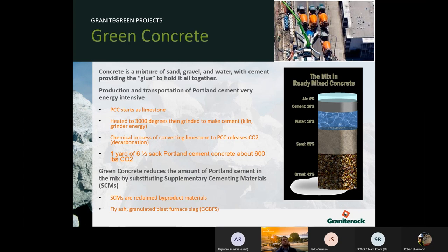To put this in perspective, 1 yard of a 6.5 sack Portland cement concrete is about 600 pounds of CO2, which is a lot. The way to make greener concrete is to reduce the amount of Portland cement in the mix by using the supplementary cementitious materials. Like we talked about, they're byproducts, and common ones are fly ash and slag.